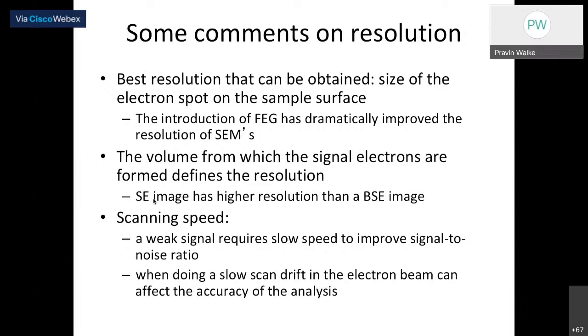So how can the best resolution be obtained using the SEM? First of all, the size of the electron spot has to be controlled in order to get more resolution, right? In fact, we observe that a field emission gun gives very high resolution compared to tungsten or lanthanum hexaboride. The volume from which the signal electrons are formed also defines the resolution, so the secondary electron image has more resolution than the backscattered electron image, right?